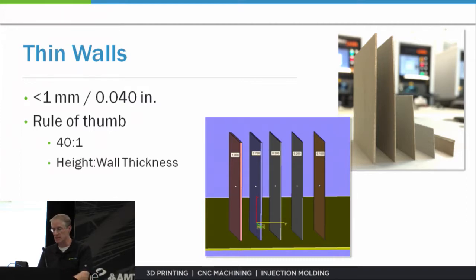So that gives us a design guideline to say, if you're designing parts for the DMLS process, you really should be focused on a 40:1 height to width ratio. And if you can achieve that height to wall thickness, you're going to have a pretty good chance of success of build on that. Now, the other thing to do is to eliminate freestanding features altogether if you can, or to brace them if need be, if they're going to be outside of this design guideline.